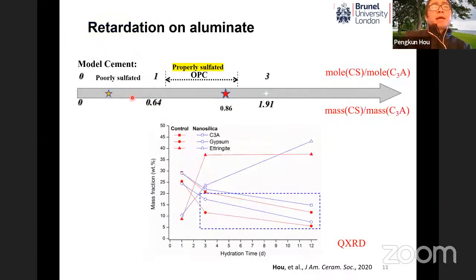So this phenomenon can also be found when the system is changed from the polysulfated system to a properly sulfated system, which, for example, has 0.64 as the percentage of calcium sulfate, that's gypsum, to C3A, which is the case in OPC. So by quantitative analysis of the C3A, gypsum and ettringite, the characteristic phases in this system, the same phenomenon, that is retardation of the aluminate phase by nanosilica, can be confirmed.